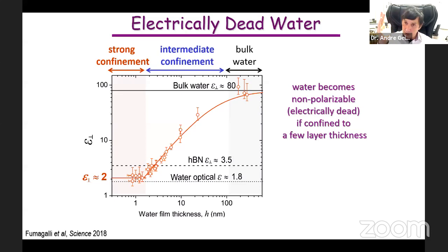And we explain this: water kind of attaches to the surface of the capillaries, although weakly. It's already polarized molecules, and then there's no rotation anymore, because in the perpendicular direction, water is already kind of ferroelectric in a sense. So fully polarized and nothing else to polarize. This is a very important observation.